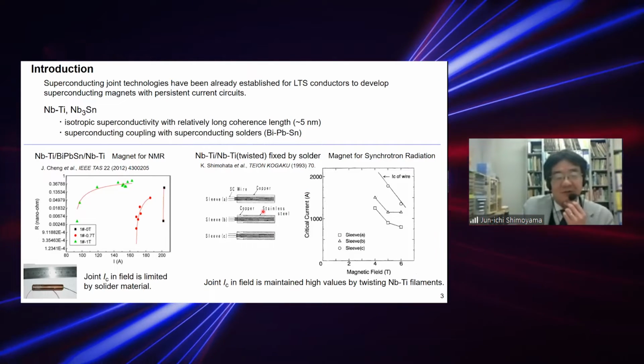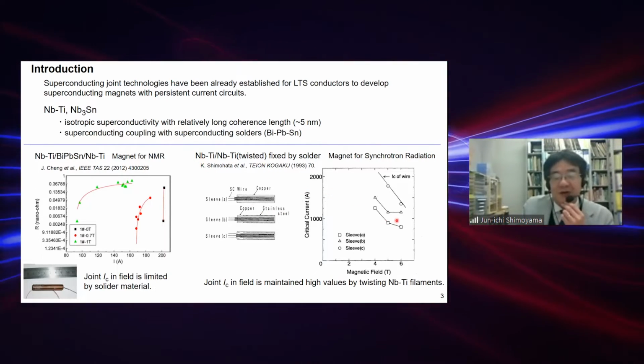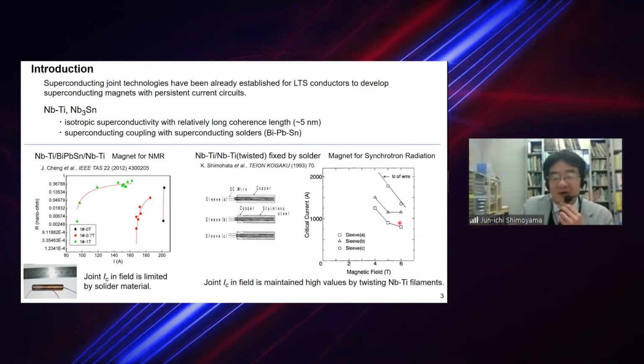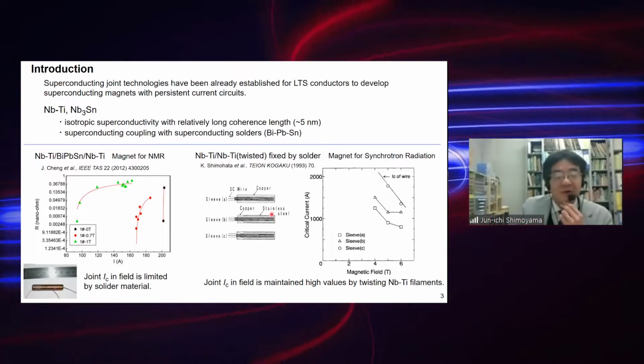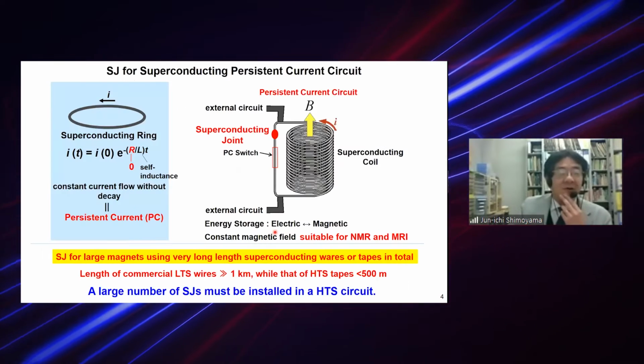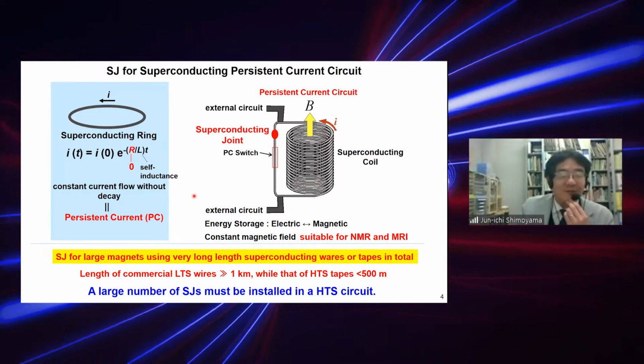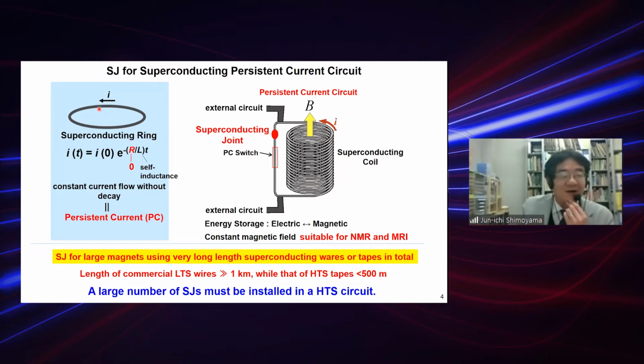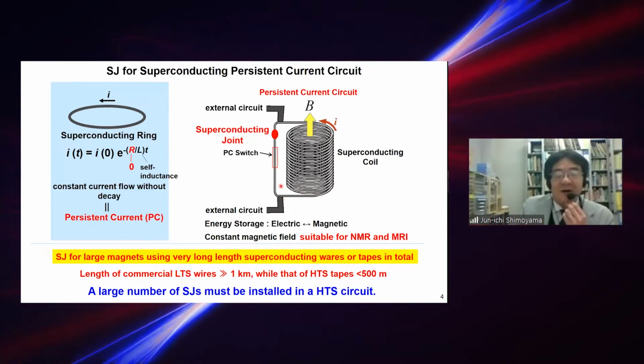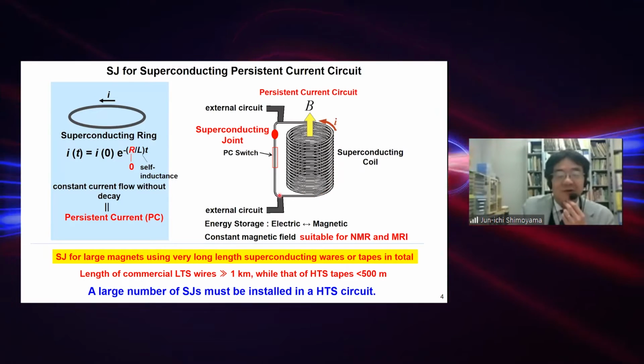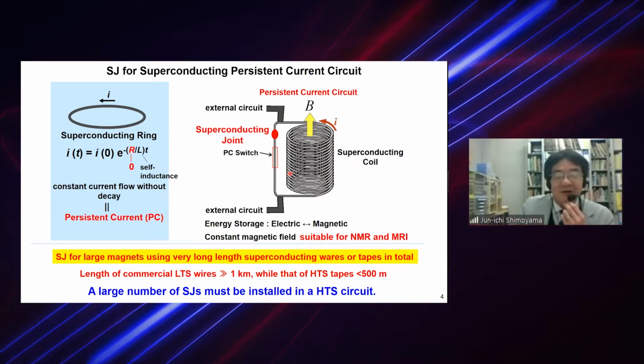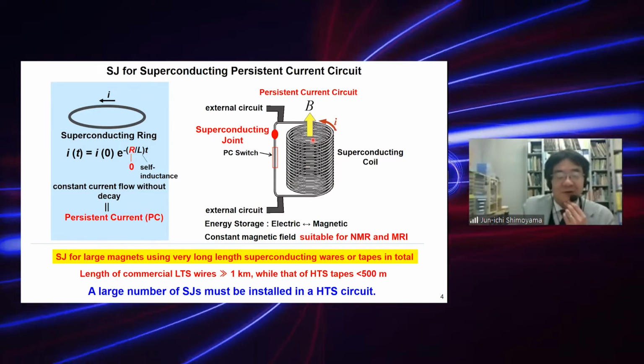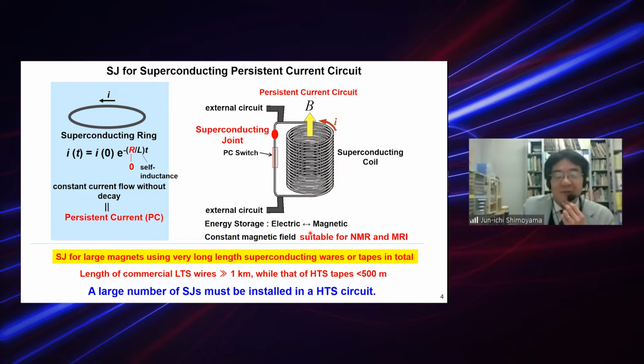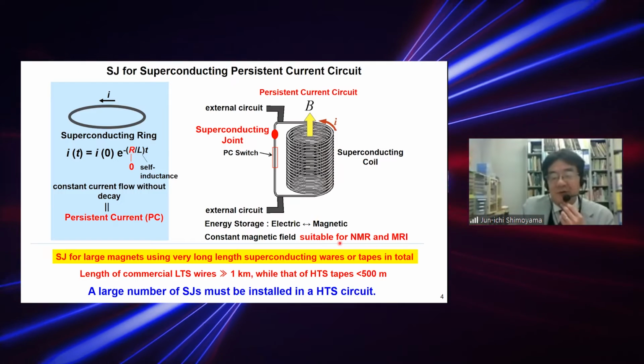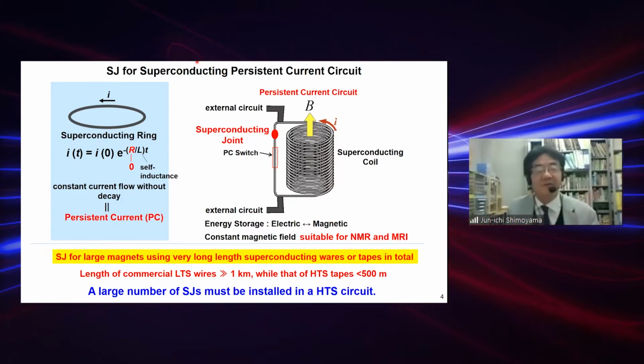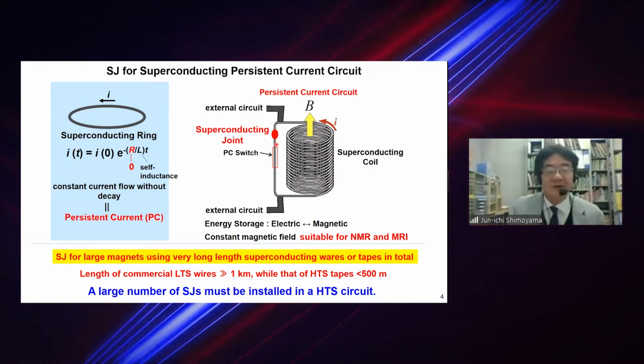In this case, direct contact between superconducting tapes improves in-field joint critical current performance. As you see here, even at 6 Tesla, very large current can flow through the joint. So this picture is a very, very primitive one. You know that the superconducting ring can carry the persistent current. But in this case, a superconducting magnet with a closed circuit and superconducting joint can save this very static magnetic field. That means energy storage between electric and magnetic, and a very stable field is suitable for NMR and MRI systems. But anyway, the superconducting joint technology is indispensable to establish the persistent current circuit.